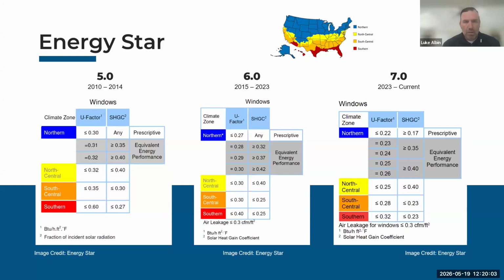May not seem like a big jump, but if you take a look, 0.08 when you're talking about U factors, but remember when we're thinking about R value too. So your R value of that window, say a dozen years ago, is about an R 3.3. Now we're looking at an R almost 5 window. That's a pretty significant jump, particularly for domestic manufacturers who have standardized on the geometry of a dual pane window system. That 0.22 number really reflects very close to the limit to which dual pane products can be, particularly again in our cooler northern climate zone.